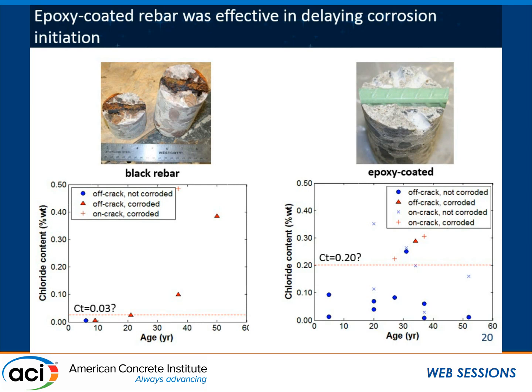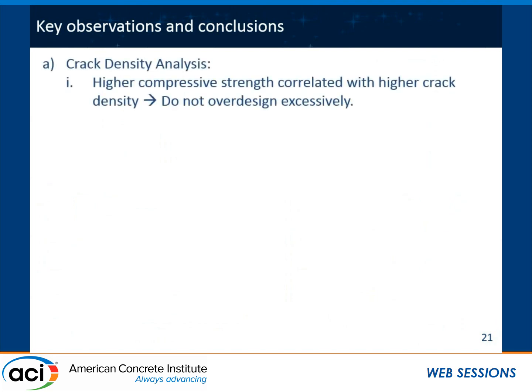So they didn't corrode until about 0.2%, both in the case of cores that were on cracks or cores that were off cracks. So it looks like the epoxy coating is helping, even in the event of cracking. Okay, so let me wrap up with some of the key observations and conclusions of the work.